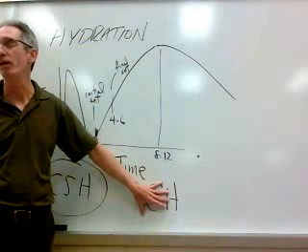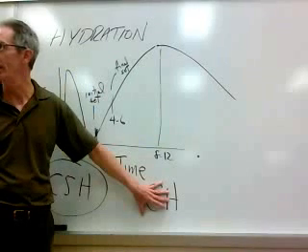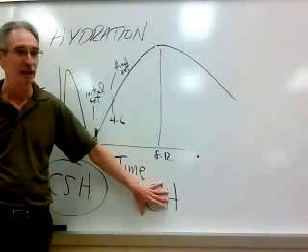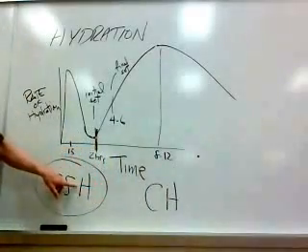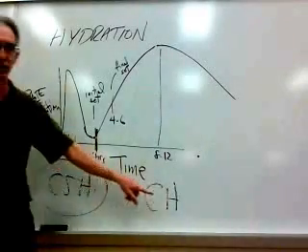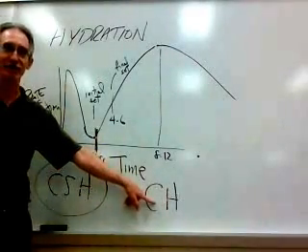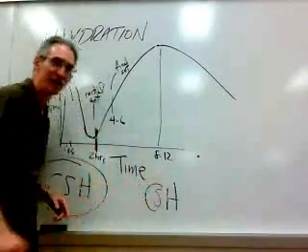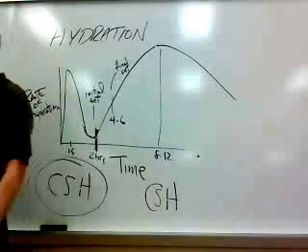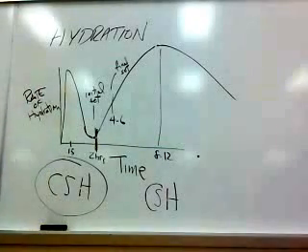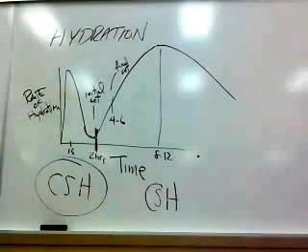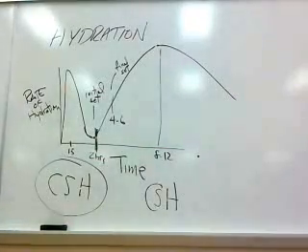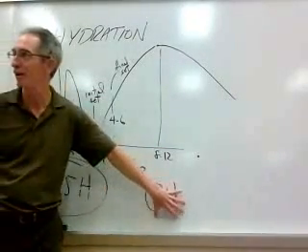What was the pozzolanic material very high in? Silicates. Some hydration forms this and this. If I put pozzolans in it, those silicates find their way here and create more CSH. That's why those pozzolanic materials are good. That's why they work. They don't work because they combine with water. They work because they combine with this.